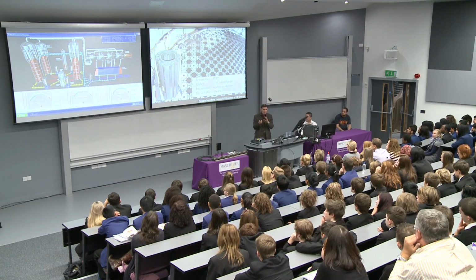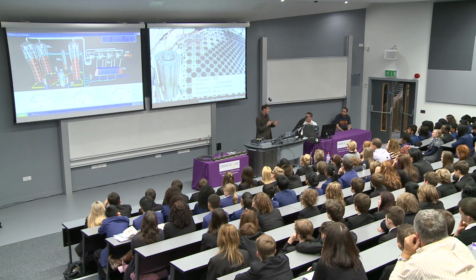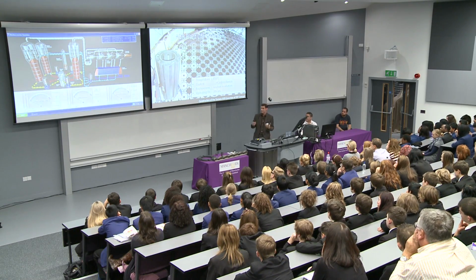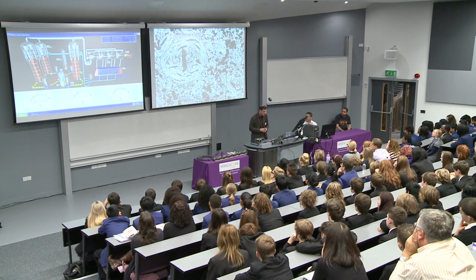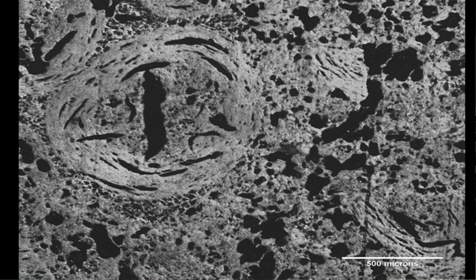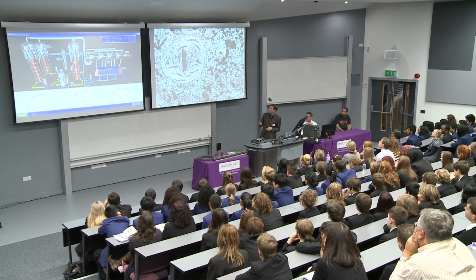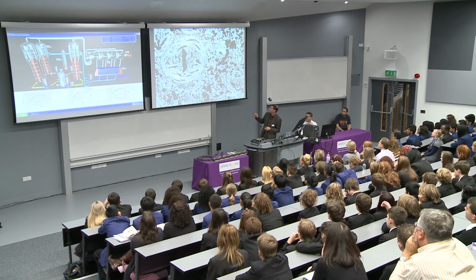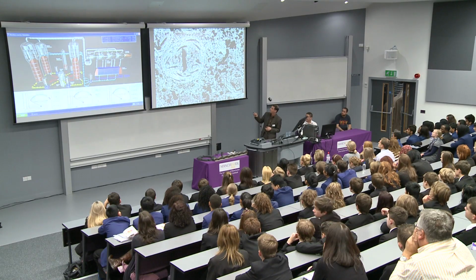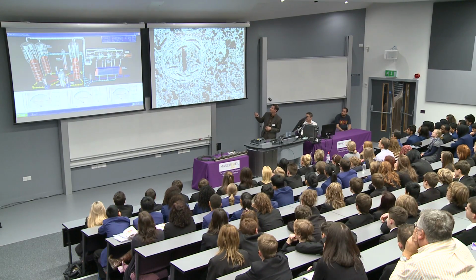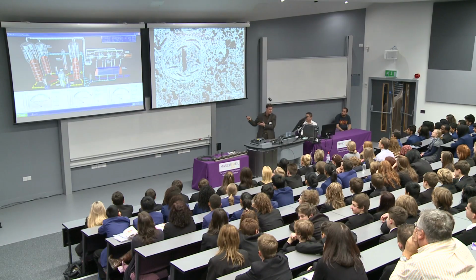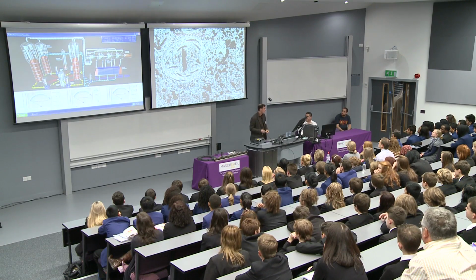So let's just look at the microstructure of graphite, because we've seen that microstructure affects how materials perform. So that's what graphite looks like, nuclear graphite, under a microscope. It's made up of a number of different components, but the thing I want you to notice is that it's full of holes. It's full of porosity, and actually, not only porosity, but within these coke particles, you've actually got cracks. And that's what the graphite looks like even before it goes into the reactor.